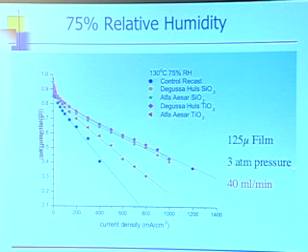We have pressurized our cell, again, because we're at a temperature where we have to be higher than the vapor pressure of water in order to get material into the cell. And this is the flow rate of the gases through our cell. And you can see that Degussa-Hüls' TiO2 wins the day, and that we have various other materials that give different responses. But all of them are better in this case than the control experiment, no metal oxide at 75% relative humidity. So this is where we're seeing the big effect.